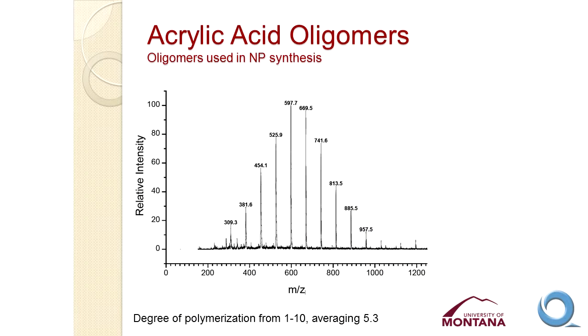The longer you allow these chains to get in controlled polymerization, the less dispersity, polydispersity you get. But since we want these short chains, we're going to have to deal with a certain amount of polydispersity in the chain lengths.